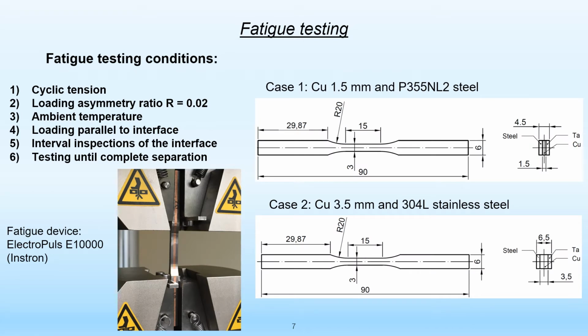Fatigue testing was carried out with the use of Instron ElectroPuls E10000 presented in the picture on the bottom left side of the slide. Cyclic tension tests were performed with a loading asymmetry ratio R equal to 0.02 in order to prevent buckling. Tests were carried out in ambient temperature with the loading applied parallel to the interface of the composite. Tests were enriched by the interval inspection of the interface with the use of optical microscopy. A failure criterion was the complete separation of the material. On the right, you can see the geometry of the specimen used for testing.